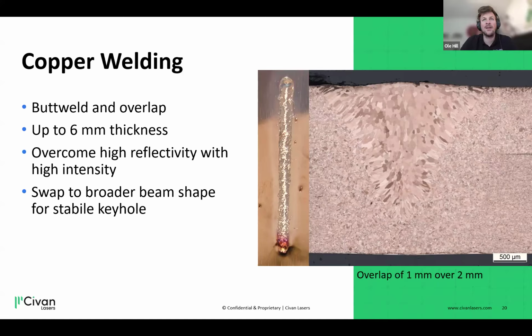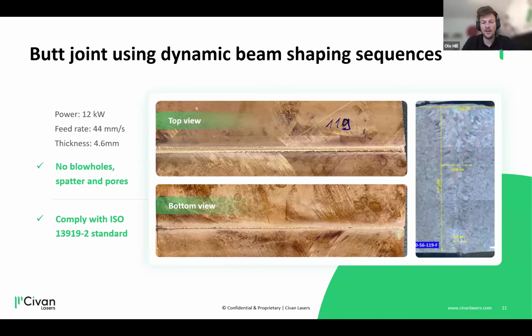We have even done fun things like an overlap of 3 millimeters over 1 millimeter. That's quite a challenge, to melt exactly 3.5 millimeters in copper, a material with such high heat conductivity. The picture on the right shows a setup of 1 millimeter over 2 millimeters of copper and a nicely shaped welding seam. On this picture, you can see much thicker copper, 4.6 millimeters, with a nice surface and bottom and a nicely shaped root. At a feed rate of 40-something millimeters per second, it's a very competitive welding speed with very nice weld quality.